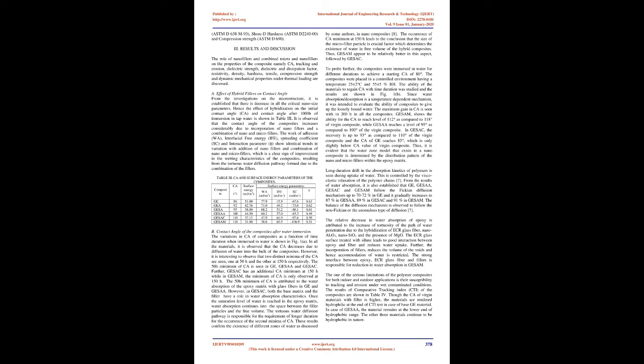C. Measurement. The parameters evaluated have been broadly grouped under electrical and physico-mechanical parameters. The method followed in the measurements is briefly discussed. Since density is an important parameter, density was measured experimentally and theoretically to estimate the void fraction of the composites. 1. Contact angle. For measurement of contact angle of the composites, methods suggested in ASTM D724 and ASTM D5946 were used. Contact angle measurements on the surface of insulating material are usually carried out to determine the surface properties of the materials like hydrophobic or hydrophilic nature and the surface energy.